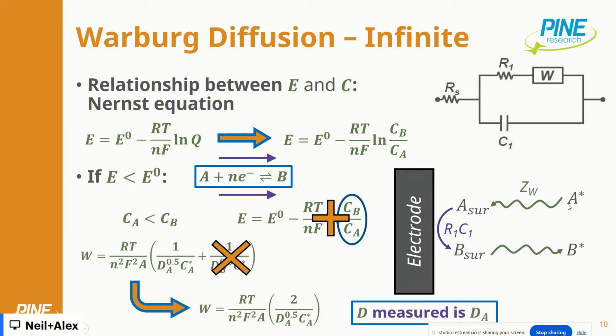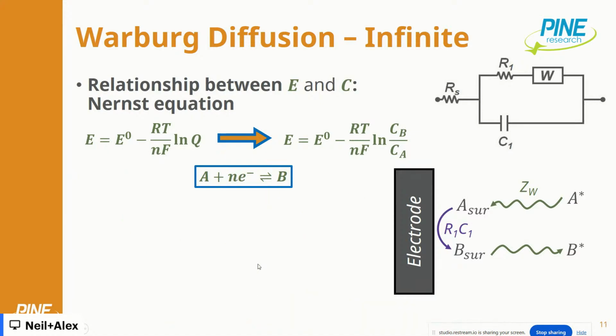So by that logic, if we are measuring Li plus electron intercalates or something like that, we want to be doing that reduction reaction, which in the case of an anode is charging. It's charging up the battery, charging up the anode. Then we would be inferring, again, to your point, like a pristine material, the lithium ion diffusion coefficient, if we're reducing the lithium to metallic lithium or to intercalated lithium or whatever it is, we are in theory at enough of an overpotential there, neglecting the diffusion of any other species, and we're studying mainly, in theory, the Li plus diffusion coefficient.